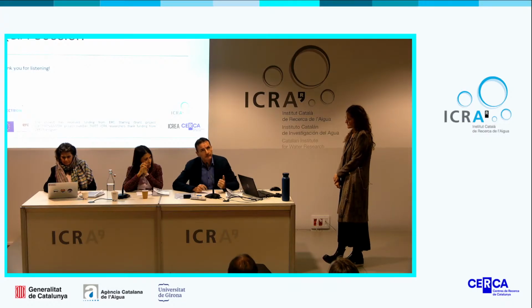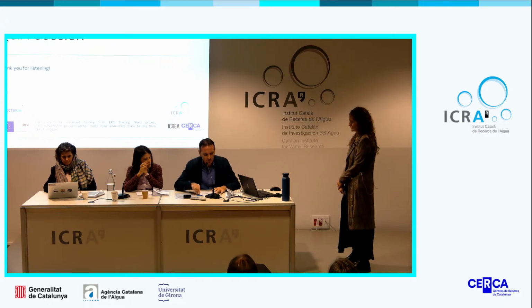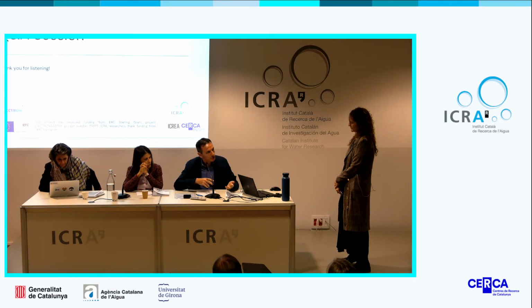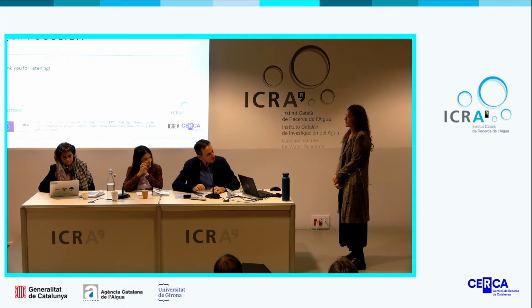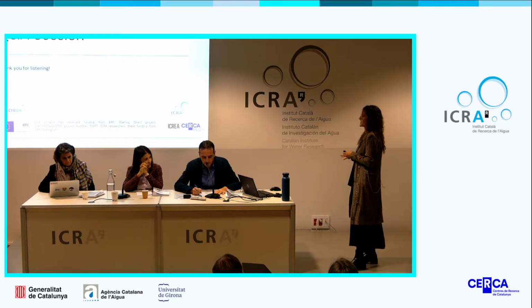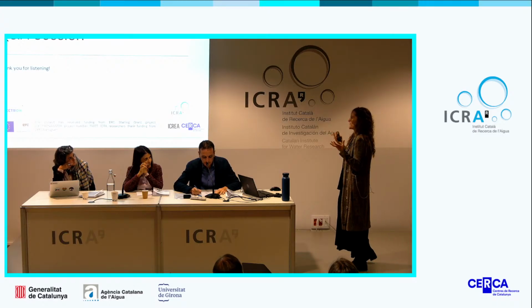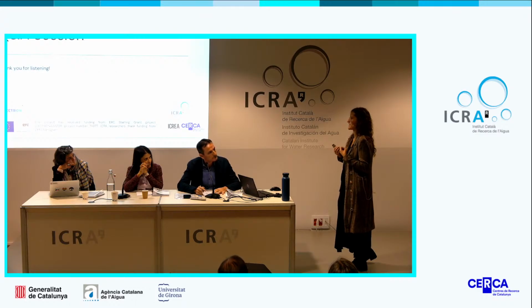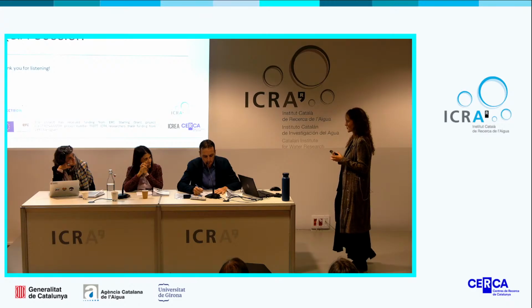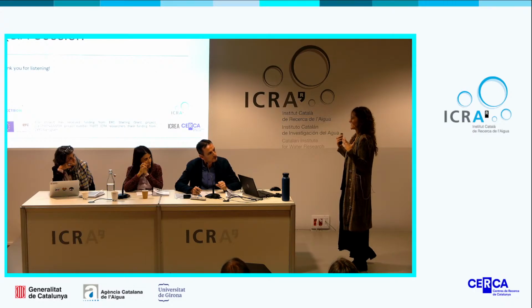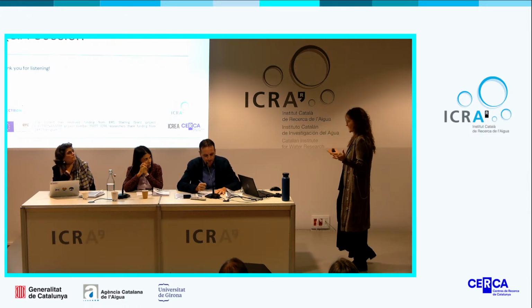Okay. So then, in the mechanisms, it's not very clear to me when the prevailing mechanism is electroporation or when the oxidants, the cathodic or anodic oxidants, have a major role or a minor role. In the case of bacteria, I will say electroporation is easy to understand as an important mechanism because, according to the scanning electron microscopy, you could clearly see it. I forgot to mention that electroporation is when a sufficient electric field creates small pores on the cell of the bacteria, where the internal part of the bacteria leaks to the outside. And this is something that we were confirming using the scanning electron microscopy.